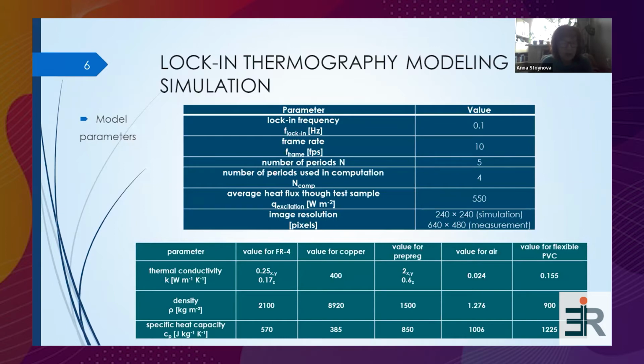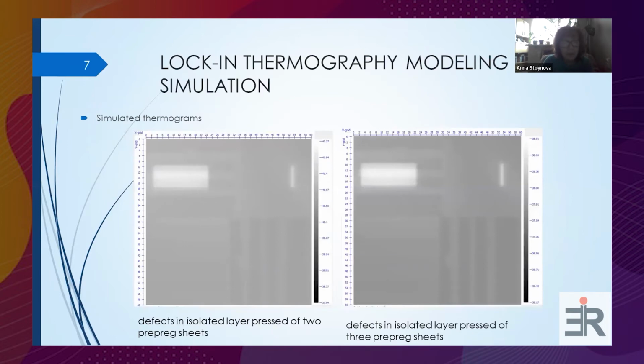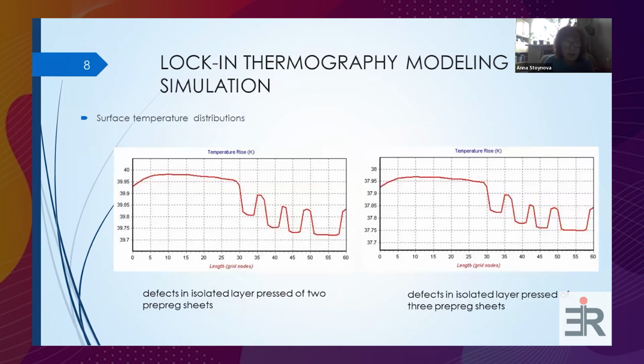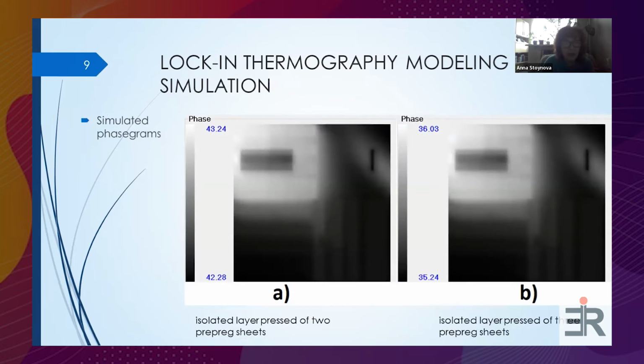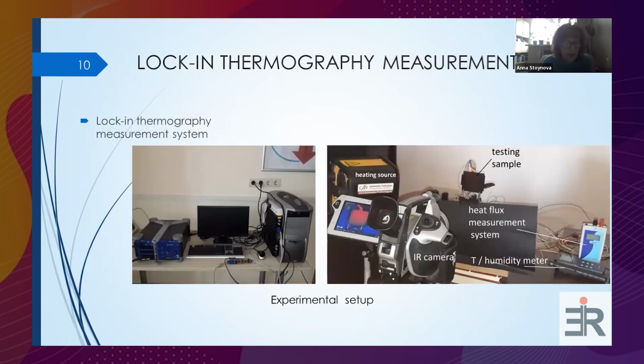Such good detection is obtained by using the results of the different models with different defects in Prepreg, also results after simulation. Here you can see the simulated defects in Prepreg after lock-in thermography simulation. The choice of thermography procedure also depends on the possible procedure we could implement. The simulation results were verified by measuring the test specimens and thermography sequences, with image processing by MATLAB Fourier transformation.